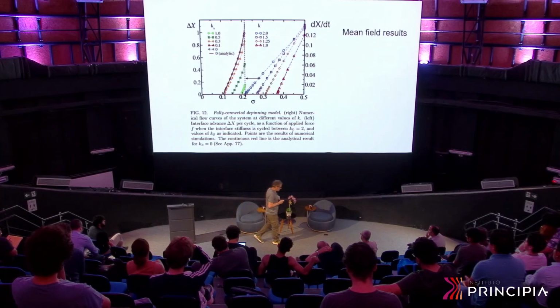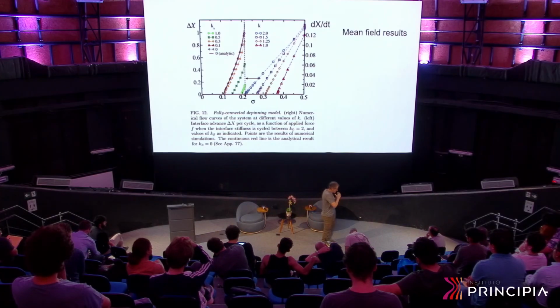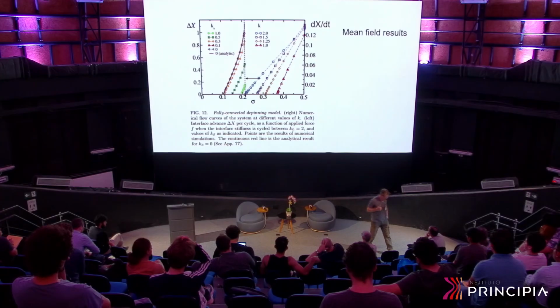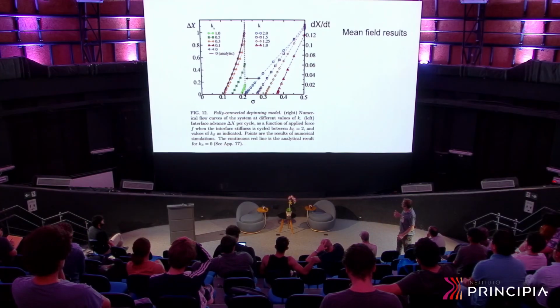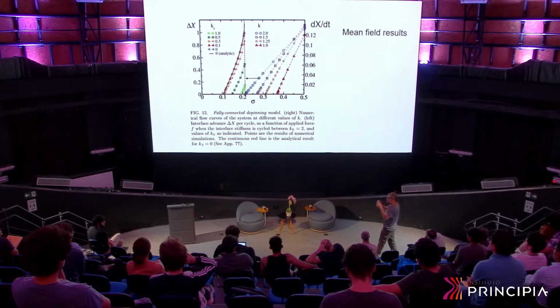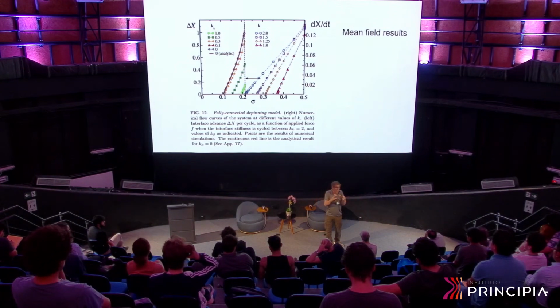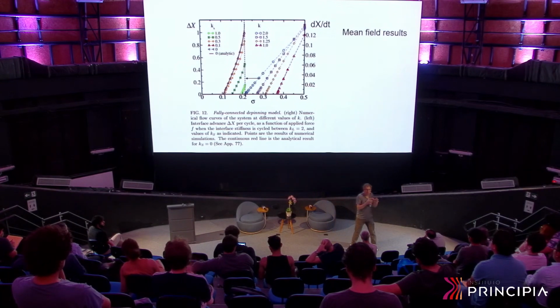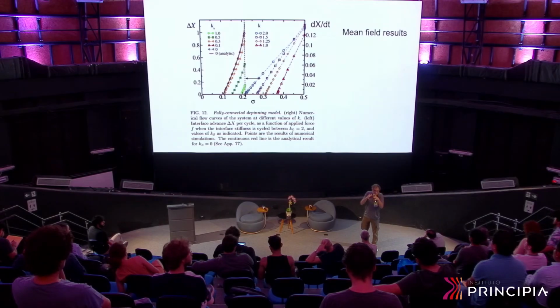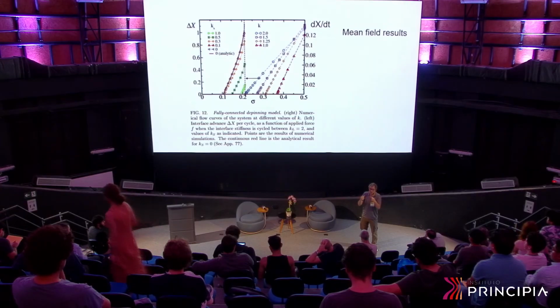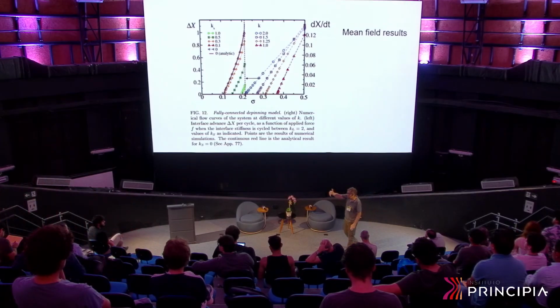Very well studied. And we think that this kind of modeling that I have presented is in some sense similar to this problem of fatigue crack propagation. Here we have this change in the elasticity of the springs in this mesoscopic model, and even if at a constant value of the spring the system would remain stable and fixed forever, when you do this cycling, the system evolves a small amount in every cycle.